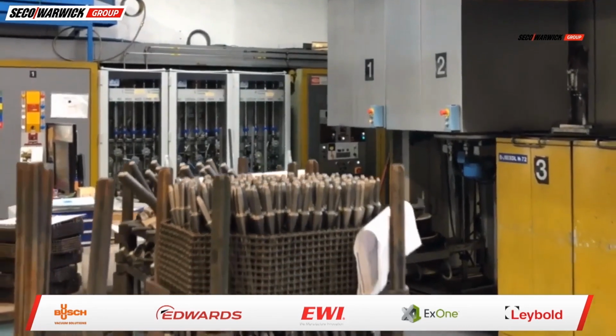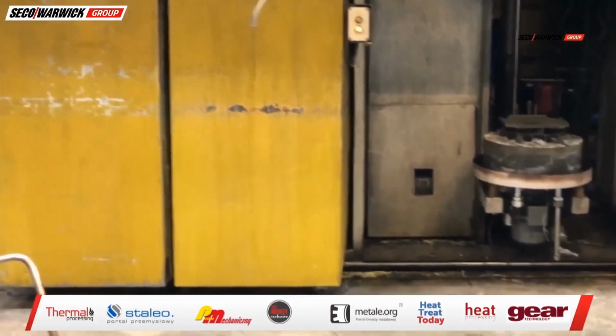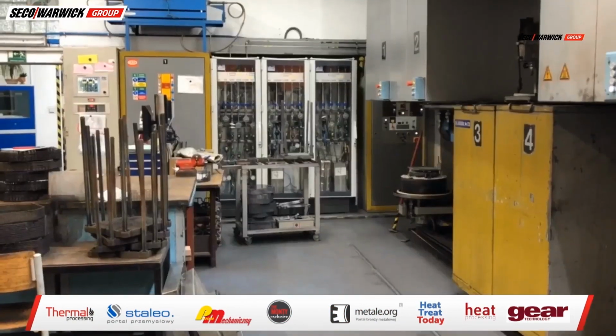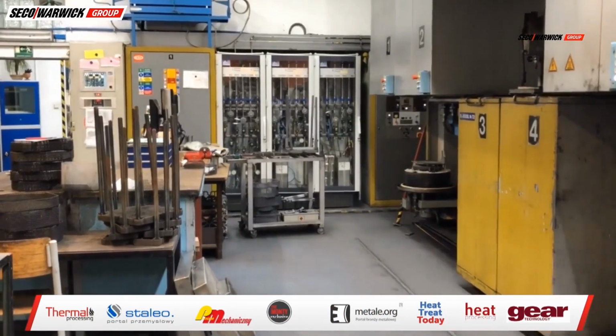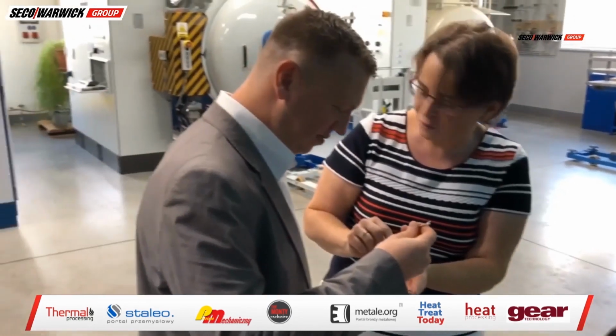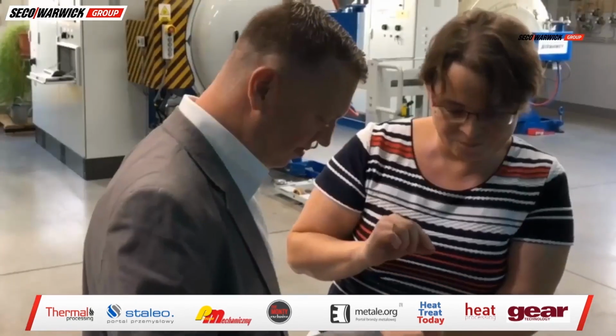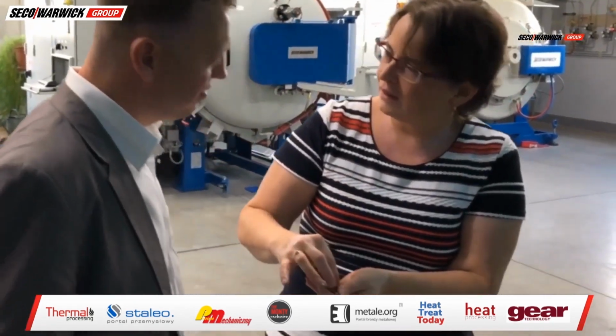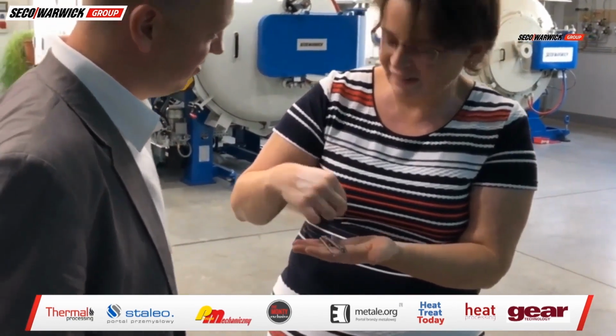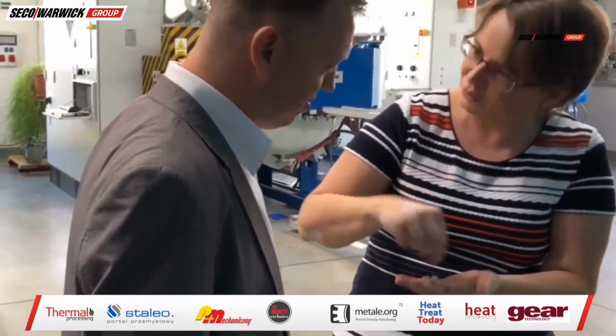Gas carburizing plus salt bath quenching produces the best mechanical properties and the least distortions, especially when the temperature of the hardening salt is high, and high proportion of bainite occurs in the structure. From an ecological point of view, it is easier to handle salt than oil.